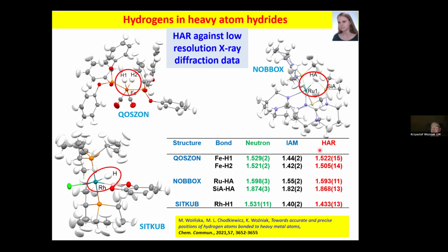And these are the distances, I mean, distances between the heavy atom and the hydrogen atom. And we've got neutron data for these systems, and so neutron results are these green ones, and Hirshfeld atom results are those red ones, and independent atom model are these ones. So even in such complex hydrides, even when we are refining against low resolution X-ray diffraction data, we are getting values which are very much like neutron ones.